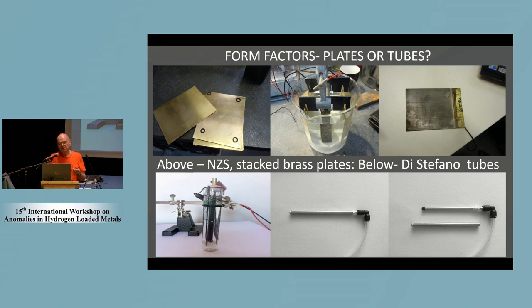One of the problems is that the electrodes tend to corrode very quickly in air, particularly if you use, say, hydrochloric acid as an electrolyte and with an iron anode. And I discovered that using alkaline electrolytes, even if I had to lace them with ammonia, for example, tends to passivate the surface, the plated surface, so you get less corrosion that way.